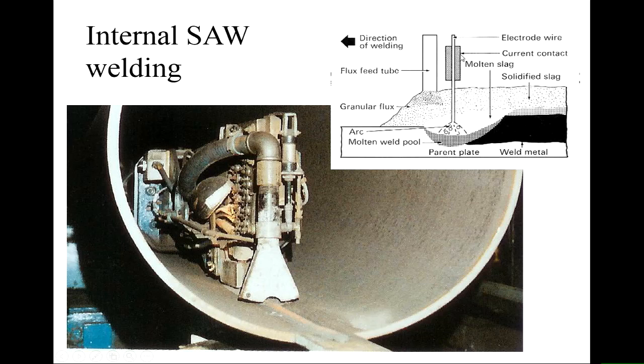So there's a picture here of a submerged arc welding process. You have a wire, and you strike an electric arc between the wire and the parent metal plate. That's the pipe that you're trying to make. And that arc, which is a mixture of electrons and ions, the electrons travel and they heat up the parent metal, and the ions travel in the opposite direction and they heat up and melt the wire. And then the molten wire particles are ejected and dropped to form the weld pool, under gravity in this case, because it's internal at the bottom of the system. So the weld metal is then deposited, molten, and it solidifies here.